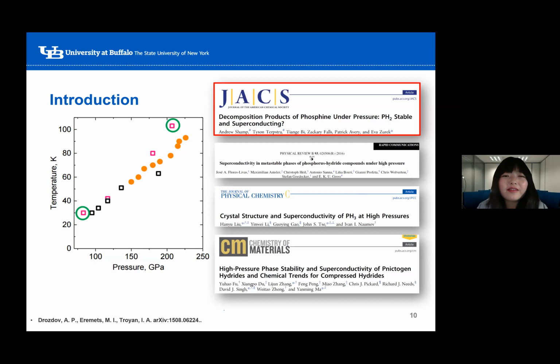As I mentioned earlier, trihydrogen sulfide was found to be a high Tc superconductor. That motivated the work on another hydride system, on another p-block element, phosphorus. So in 2015, Drozdov and co-workers observed a Tc of 103 Kelvin at 207 GPa after loading phosphine into the diamond anvil cell. The lack of structural information from the experimental paper encouraged us to carry out our computational study on this system, and we were among the earliest to publish the results. The following papers came out around the same time.